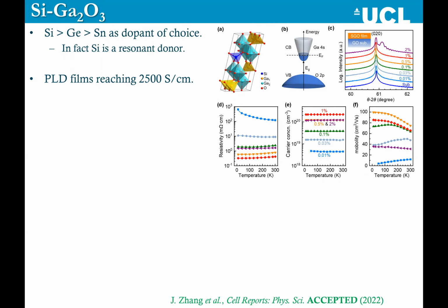But up until this paper, people had only ever managed to get about 700 Siemens per centimeter of conductivity. And we have shown that that was simply a limitation of how they were growing the system, and that these PLD grown films have reached 2,500 Siemens per centimeter. So this actually pushes this material beyond even just power electronics, but now can be thought of as a transparent conductor, just like tin dioxide and doped indium oxide, and therefore you can have it as an ultra wide band gap transparent electrode. So this is going to open up new avenues for gallium oxide research.